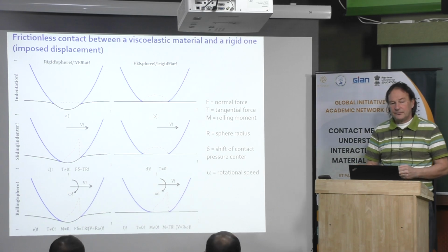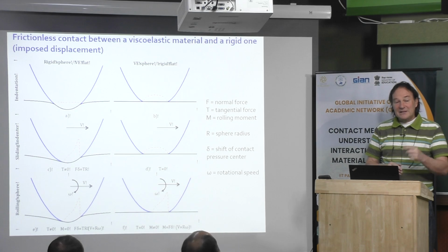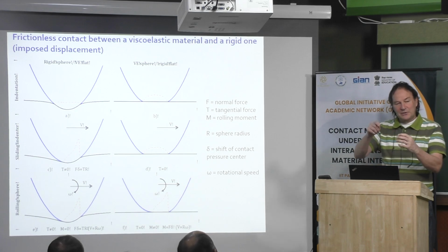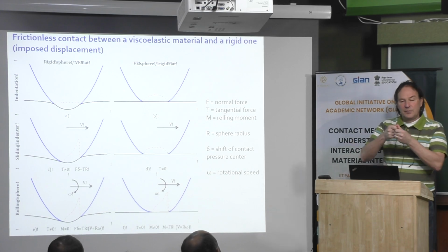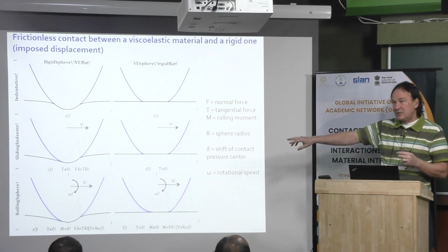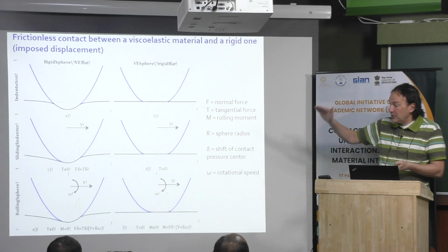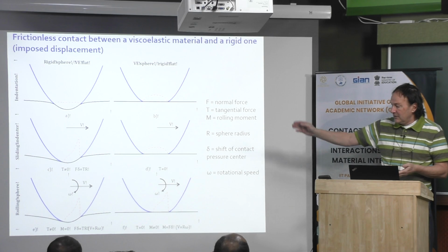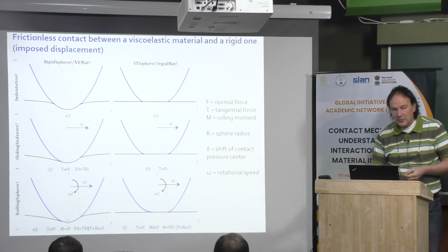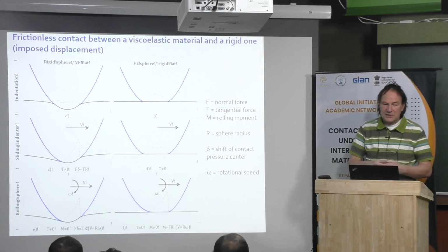Also, is it not because the material is collecting on the front side? No, there is no ridge at the front side. When it is elastic-plastic, yes, you create some front, which you can see when you unload, maybe not when you load. When you see this type of picture for an elastic-plastic material, this is a total deformation, both the elastic one plus the residual deformation. But here there is none. When you unload, suddenly the contact will have the same shape, but after a few microseconds or milliseconds or seconds, it will go back to the initial shape. This is a viscoelastic behavior.